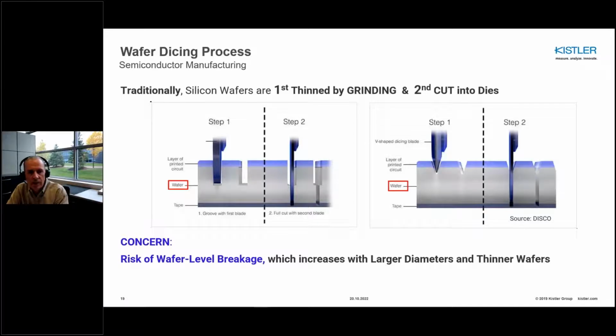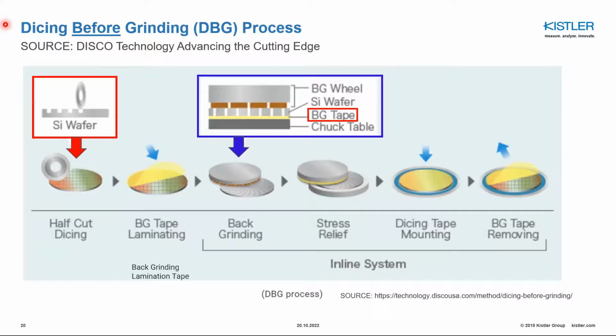Here we're looking at a traditional wafer dicing process whereby the wafers are first thinned by grinding and then they're cut into dies. The challenge is that as the workpiece gets thinner, dicing increases the likelihood of damage. In dicing before grinding, I will only focus on the first 3 steps here. In the first step, in the red box, the wafer is half cut or slotted. This is where dicing is performed.